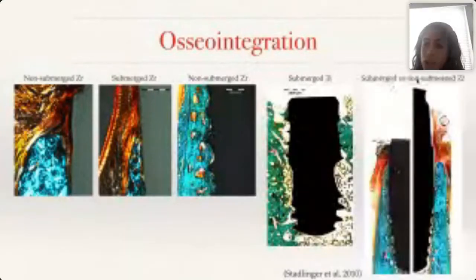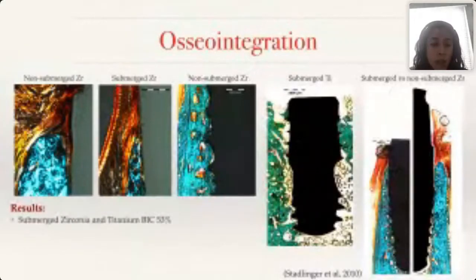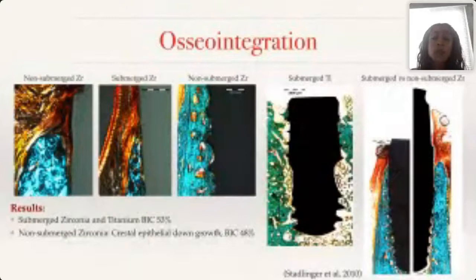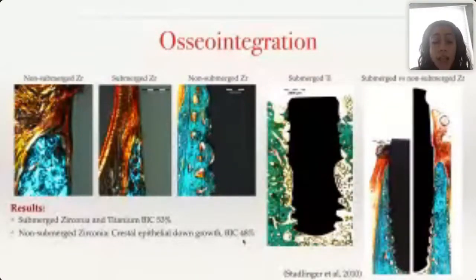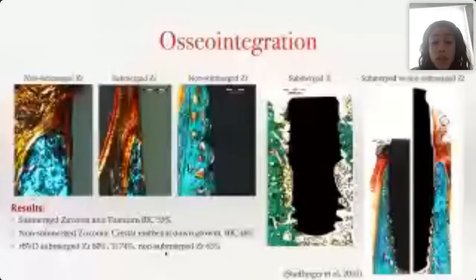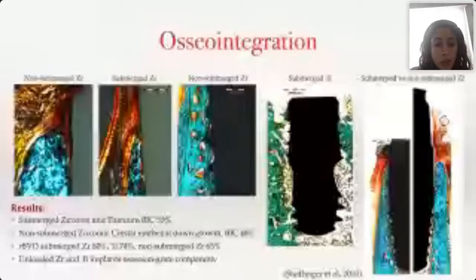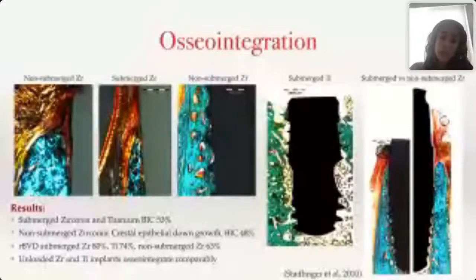And lastly, the submerged versus non-submerged zirconia. The result was both submerged zirconia and titanium implants had bone to implant contact of about 53%. There was crestal epithelial downgrowth in the non-submerged group, which reduced the BIC slightly. Relative bone volume density was actually higher around zirconia compared to titanium, but with no significant difference. The study concluded that they both osseointegrate comparably.